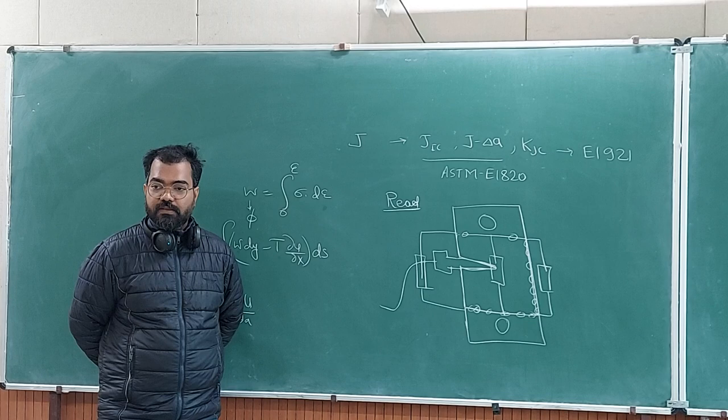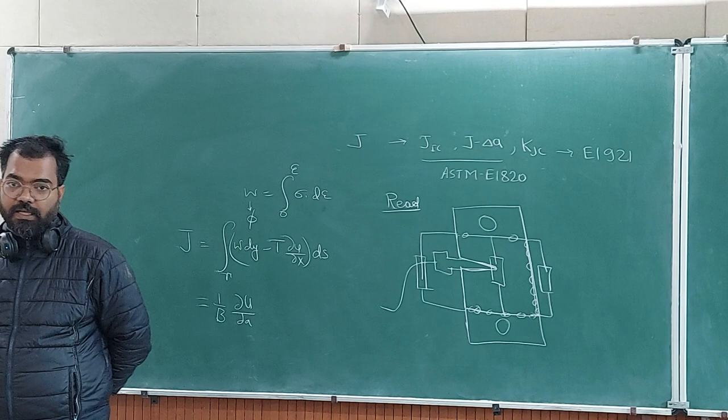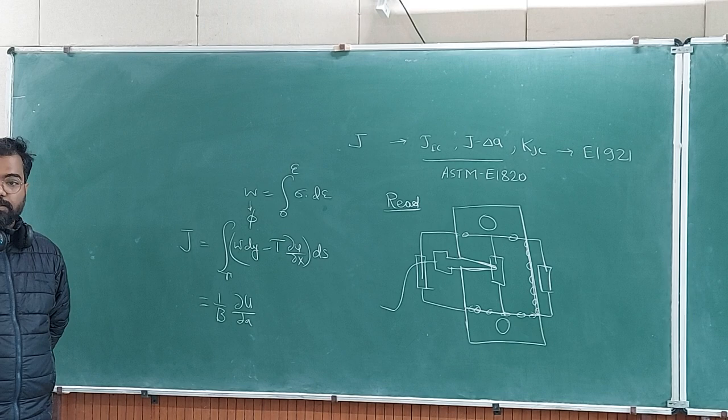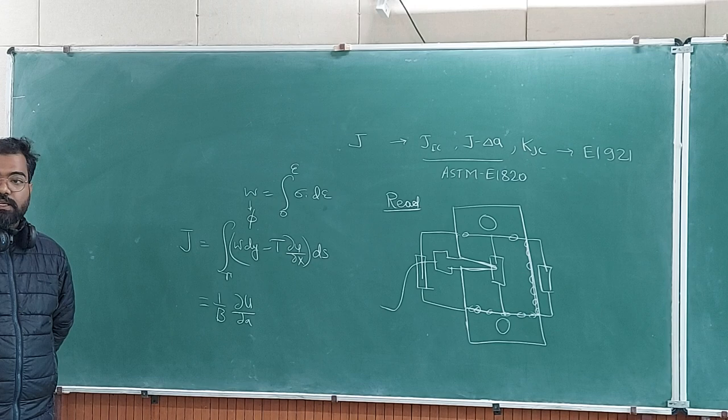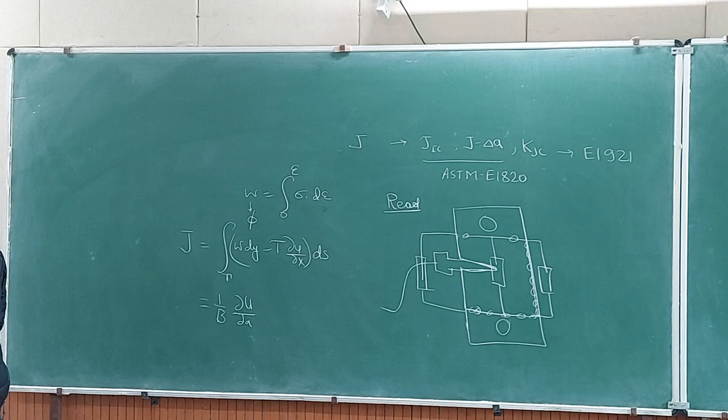But this kind of testing is very cumbersome. In one specimen, you have to put a lot of small strain gauges, big strain gauges, 3-4 LVDTs, a COD gauge, and then you have to do the line integration at different points with an approximation that interpolates linearly between the two measurement points. So this is not practical, but it is done.